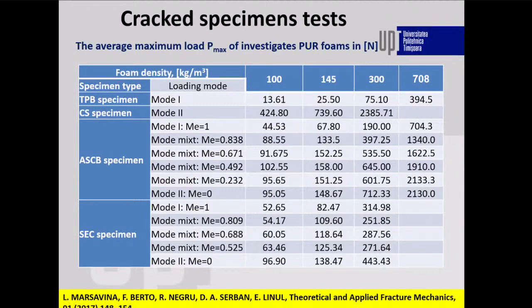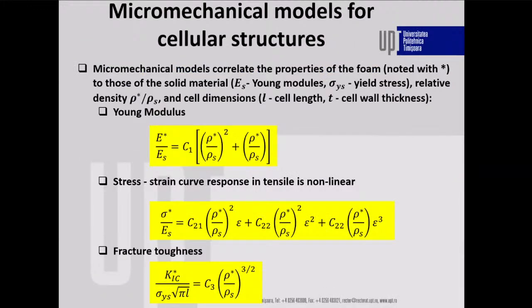This is only a summary of the average maximum load for all the tests that we did. Usually we did 4 or 5 tests for each combination, for each mixed mode, and for each type of specimen. Then we tried to calculate the strain energy density parameters, the critical strain energy density and the control volume. We tried to find these using micromechanical models, which are used to express the property of cellular materials based on the property of the solid material and on the relative density of the foam.